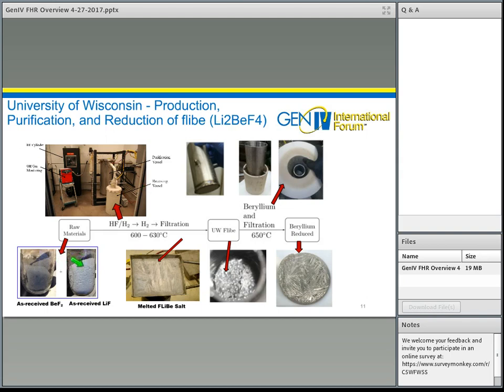So what you see here is the ingredients being received at University of Wisconsin and then purified with HF and hydrogen at Wisconsin, resulting in purified salt, and then also a variety of different processes that have been studied to control the redox potential of the salt, to reduce corrosion rates, and then the experiments to perform corrosion testing with these materials.